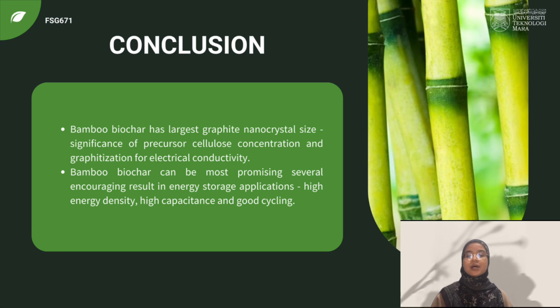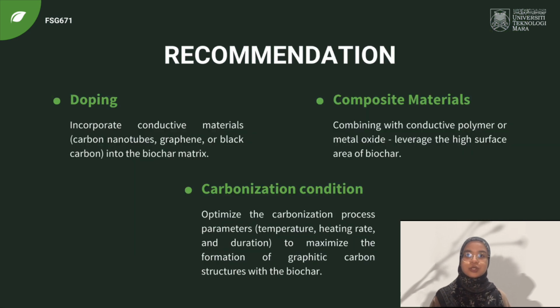So, for conclusion, bamboo biochar has the largest graphite nanocrystal size, which is significant for precursor cellulose concentration and graphitization for electrical conductivity, and bamboo-derived cellulose was thought to be one of the most promising sources of cellulose that shows several encouraging results in energy storage applications, which are high capacitance, high energy density, and good cycling stability. However, to improve the bamboo biochar's performance, take into account the following suggestions.